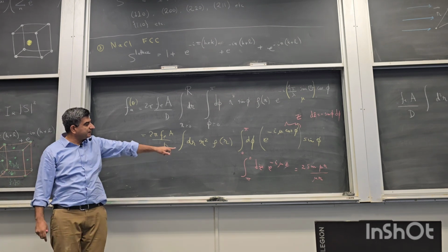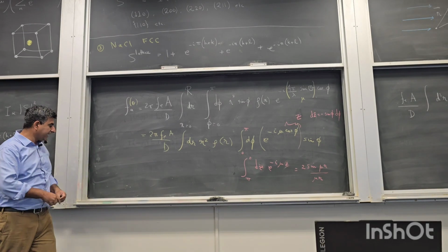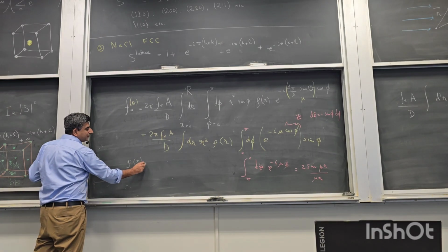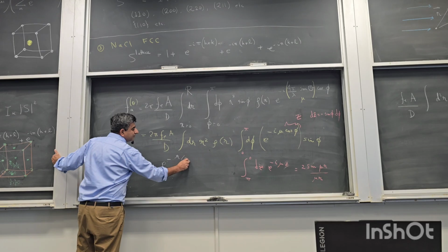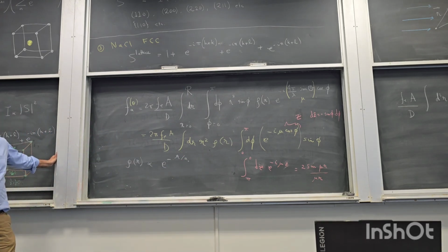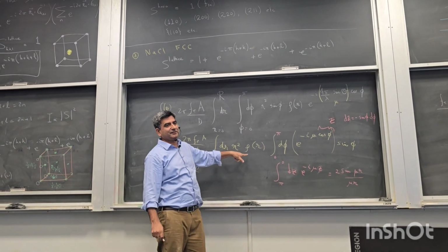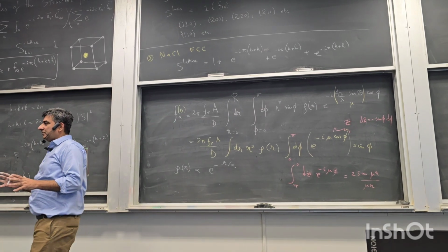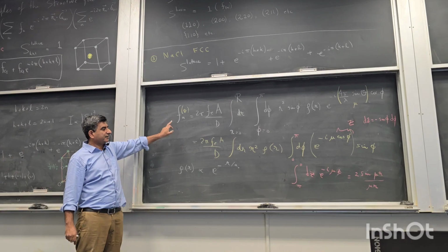And I can put in explicit values of the probability density function. For example, for an s orbital, rho is proportional to e raised to power minus r over some factor which resembles the Bohr radius. So I can put this value in here and compute this for different kinds of electron distributions. This will give me the theta dependence of this atomic scattering factor.